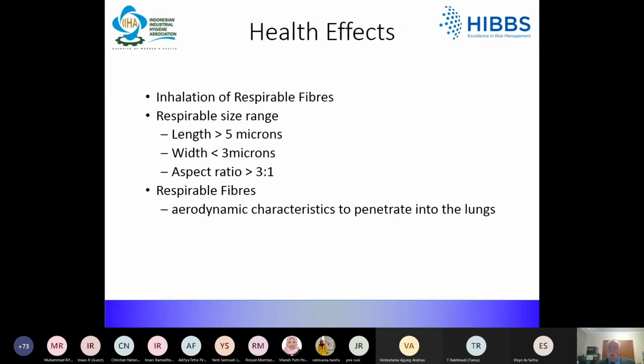Because of the nature of asbestos, when the fibres are ruptured, they split along the length of the fibre and produce long rectilinear fibres that are very, very fine in diameter. So the respirable size range is defined as those fibres that are greater than 5 microns in length, less than 3 microns in diameter, and have a length to width ratio that's greater than 3 to 1. And it's fibres in that size range that possess the aerodynamic characteristics that allow them to penetrate down to the gas exchange or the alveolar regions of the lungs.